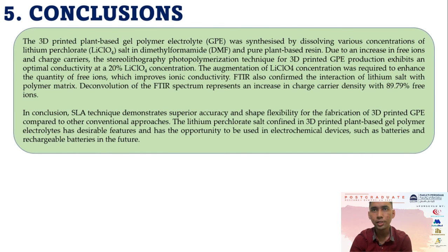Due to an increase in free ions and charge carriers, the stereolithography photopolymerization technique for 3D printed GPE production exhibits an optimal conductivity at 20% concentration lithium perchlorate. The augmentation of lithium perchlorate concentration was required to enhance the quantity of free ions, which improved the ionic conductivity. FTIR also confirmed the interaction of lithium salt with the polymer matrix. Deconvolution of the FTIR spectrum represents an increase in the charge carriers density with